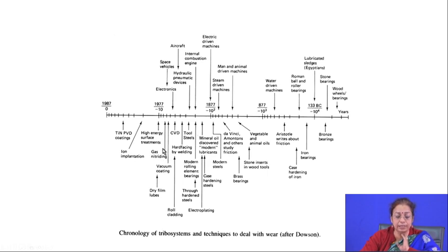Then the vacuum coating technique came into the picture in 1977, and after the invention of laser and electron beam, people started applying laser cladding, laser surface treatment processes, and then ion implantation and PVD coated substrates. So, right now if you just see the scenario, people do apply weld overlaying, nitriding and carburizing processes, different laser, electron beam or plasma based processes, as well as physical vapor deposition and chemical vapor deposition techniques in order to improve the hardness of the surface, and as a result they get improved performance of